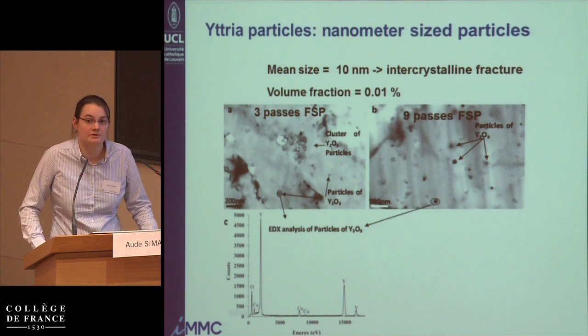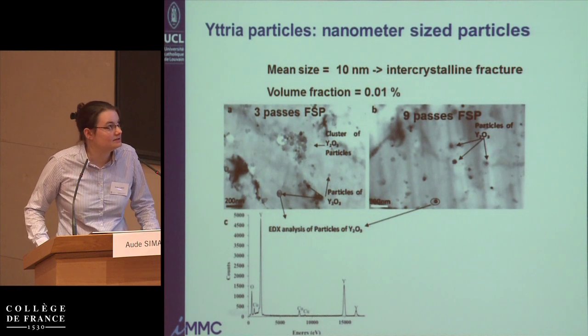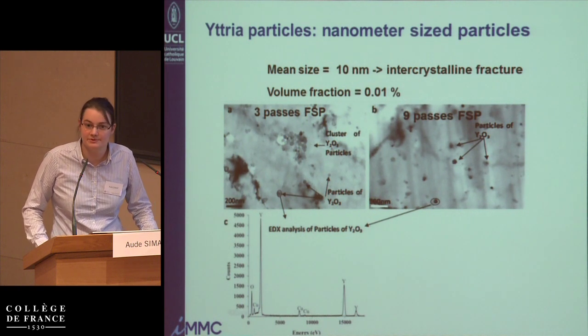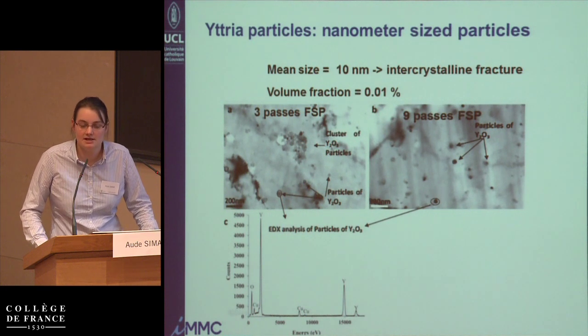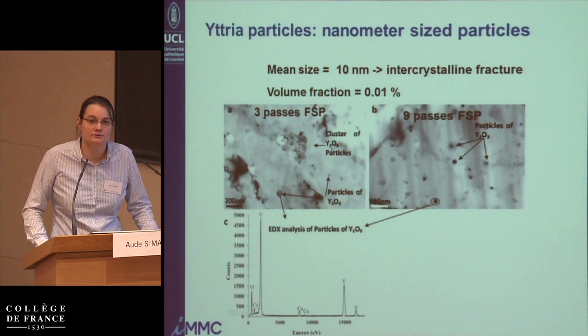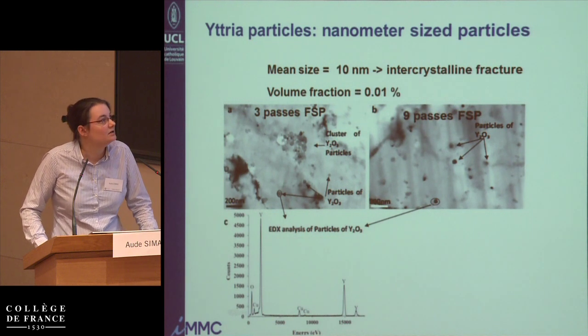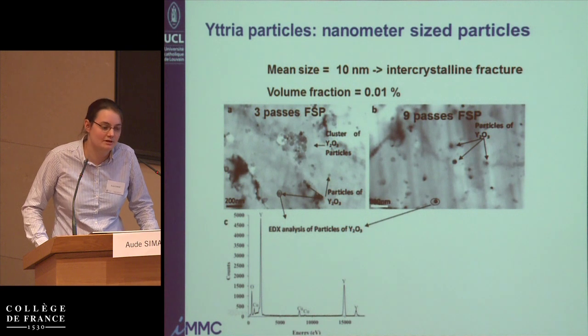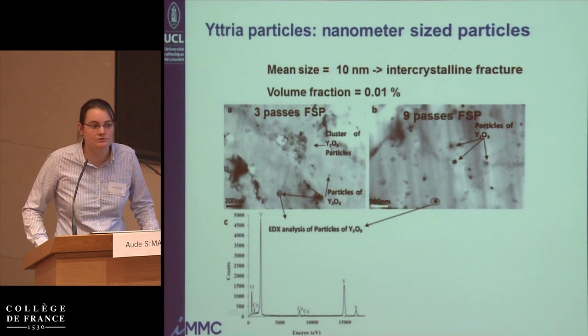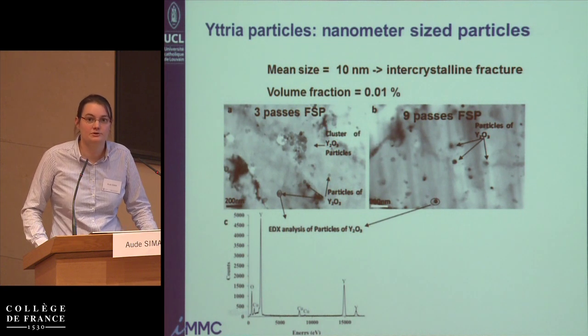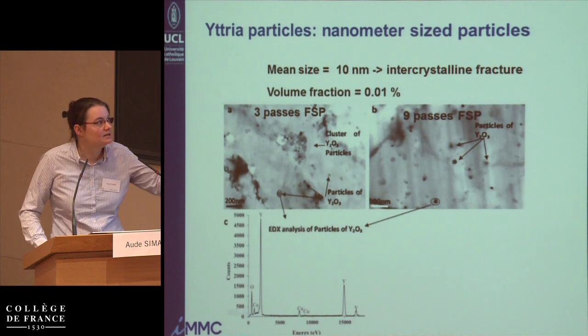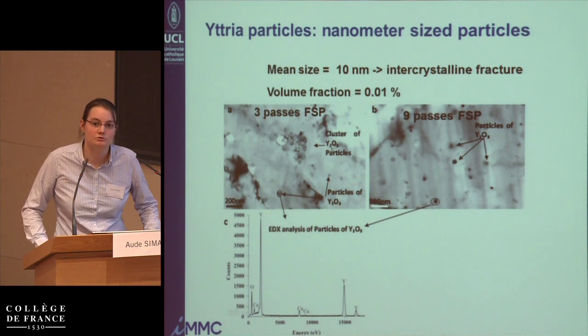Now, the disappointing thing here is that the volume fraction is still 0.01% of these very small particles. It does have an effect, and when you look at the volume fraction of precipitates in aluminum alloys, for example, you are at very low volume fractions, typically of this order of magnitude, or maybe a little larger, and it does have a huge impact. So when you have nanoparticles, you don't need to have a very large volume fraction to still have an effect, but we're still not at the level that we could hope. But these are very encouraging results.